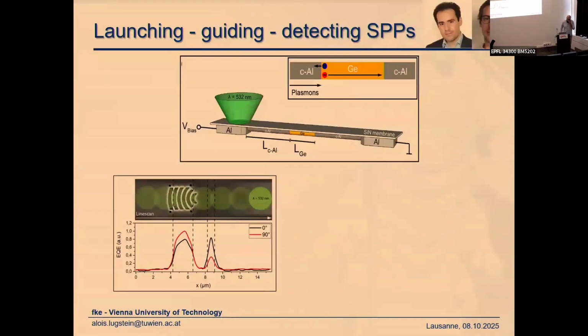So we now transferred this structure onto a thin membrane, as is shown here. That was a 30 nanometer thick silicon nitride membrane. And in this membrane, we patterned a focusing grating coupler with the focused ion beam. The idea was now that we excite some plasmons in this grating, which propagate along this aluminum nanowire, and then they should decay at this germanium interface, and we can somehow detect the hot charge carriers which are generated here. So the simple experiment was that we scanned with the laser along the structure, and we measured the current between these two pads.